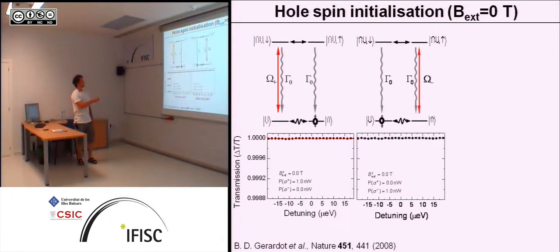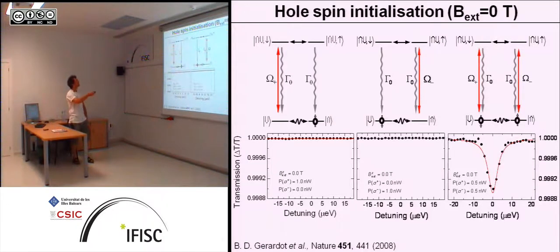Then we change the polarization, pump with sigma minus, and again the same happens. But I mean, everybody can create a system which doesn't interact. That's just an error in the experiment because you produce such a result. But what we can do now is we pump with both lasers at the same time, and then each laser frustrates the storing mechanism of the other laser. And there suddenly you get this whole interaction back. And that basically is the confirmation that you successfully stored population in that state or in that state, because you can now basically destroy the same mechanism.